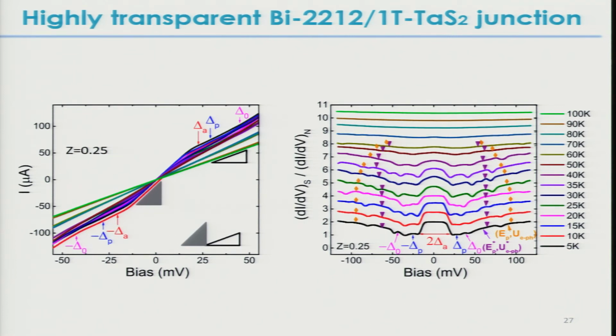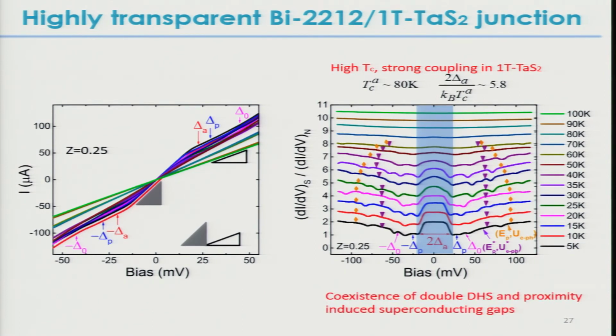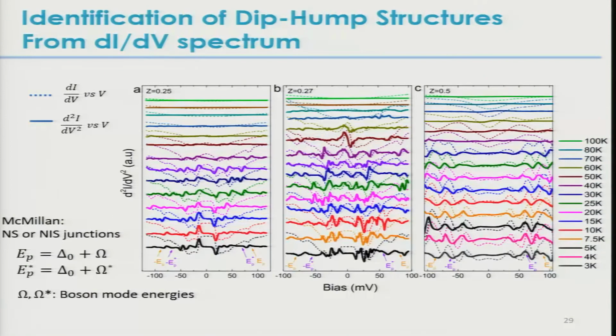I don't have time to go over this, but we do spectroscopy and look for maxima. And we see in the second derivatives, as in the work that Bill McMillan and John Rowell did in getting the phonon contributions to superconductivity. The long and the short of it, this again is 5 Kelvin, is that it's strong coupling for the induced gap here. It's 5.8. So the gap is pretty big, and the TC is fairly high, as you'll see. So we see some double dip hump structures. I don't have time to go through this because I want to get to some other things.